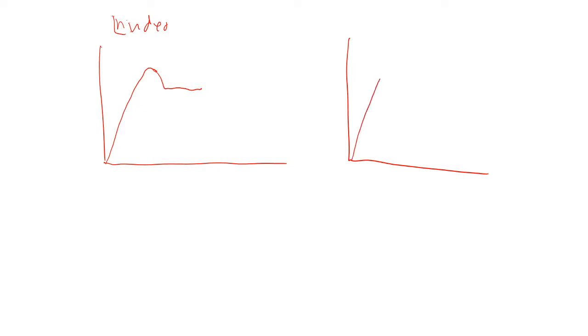tensile stress. First, both the Lüders band formation and the neck initiation are based on the formation of plastic flow at the gauge length. And second, for both the mild steels and the polymers, the stress required to initiate the plastic flow is greater than the stress required to continue it. This is the mild steels, the Lüders band formation. And this is the neck initiation of the polymer. And third, for the mild steels, the work hardening occurs once the plastic flow has propagated